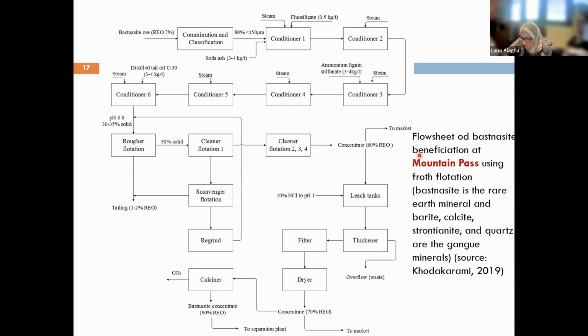So after these 6 stages of conditioning, the feed goes to rougher flotation. And you can see here the pH is about 8.8 and the solid concentration is 30 to 35%. After rougher concentration, the first stage of concentration, the concentrate that has rare earth mineral goes to cleaner flotation to further clean your concentrate.